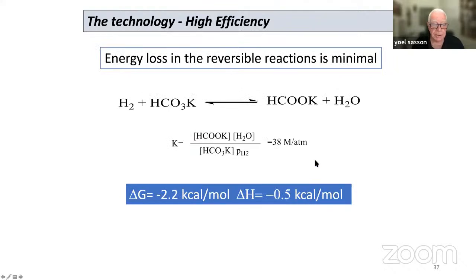Now, this is the reversible reaction and the equilibrium constant, but most important, the free energy and the enthalpy close to zero in both cases indicate that the reaction is very reversible. It's almost the same - you can go from here to here just by switching the pressure of the hydrogen. On top of that, the energy you consume for this transformation is minimal, 0.5 kilocalorie per mole, very, very low.